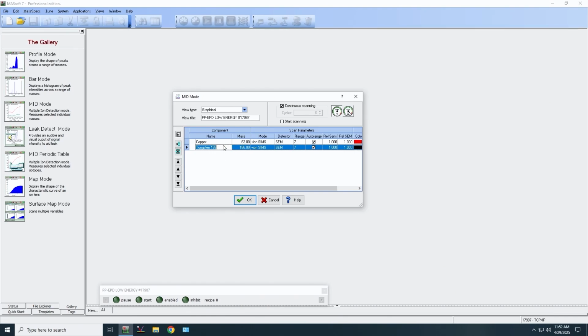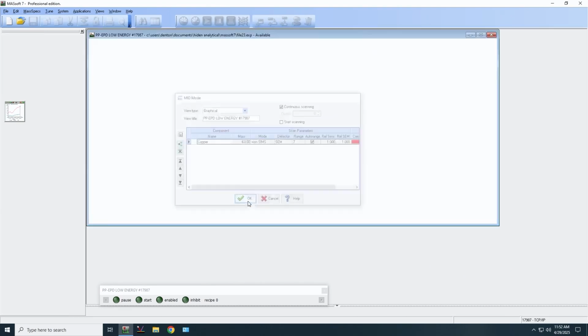So the other material on this chip is silicon, but unfortunately you can't monitor silicon because its mass is 28, which is the same as background nitrogen. So N2 is 28. If you tried to monitor silicon, you would just get a very high signal, and you can't really see the silicon start and stop. So I'm going to delete that row, and we're just going to look at copper. So I'm going to press OK.